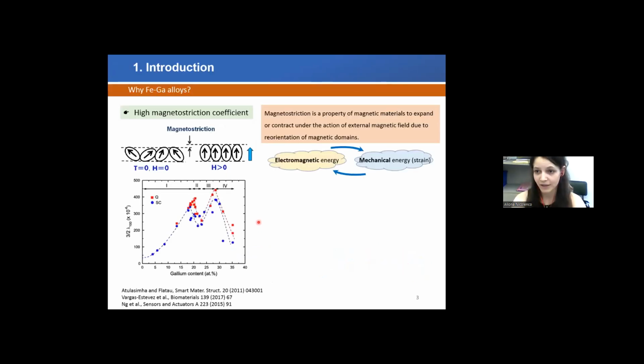So why iron gallium films? In fact, the main property that we're looking for in these alloys is their high magnetostriction. So what is magnetostriction? It is a property of magnetic material to expand or contract under the action of an external magnetic field, that actually occurs due to the reorientation of magnetic domains when the external field is applied. So this property, in fact, allows a conversion between electromagnetic energy and mechanical energy or strain, and that's why these films, iron gallium alloys, are widely utilized for the fabrication of various sensors and actuators.